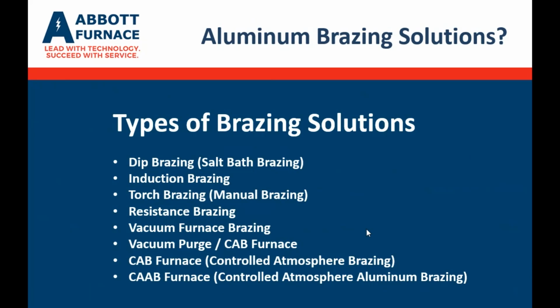Then you can add a vacuum purge option to an atmosphere furnace by evacuating the air out of the furnace and then backfilling with atmosphere, or in the case of aluminum brazing, nitrogen, with the vacuum purge CAB furnace combination. Or you can have the straight CAB furnace and controlled atmosphere brazing, which utilizes a nitrogen atmosphere. In the market you'll sometimes see it referred to as CAAB, controlled atmosphere aluminum brazing, essentially the exact same thing as CAB furnace brazing.